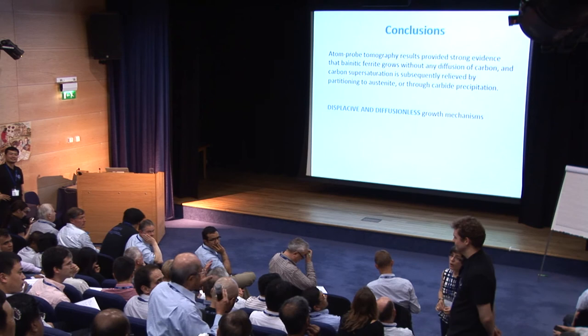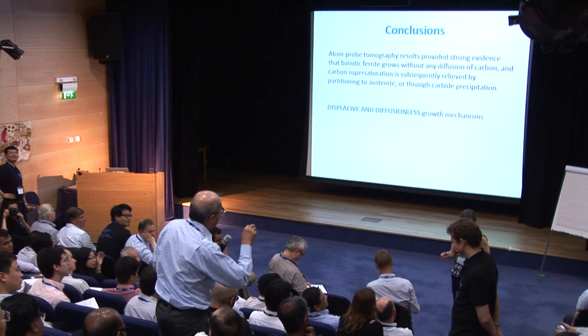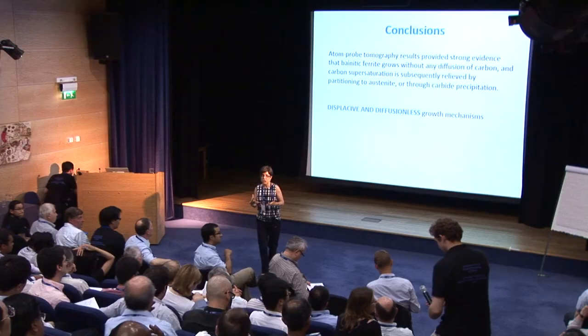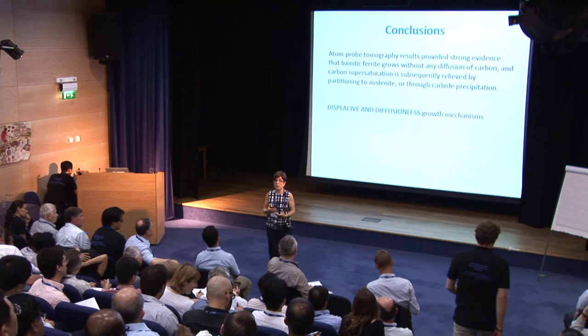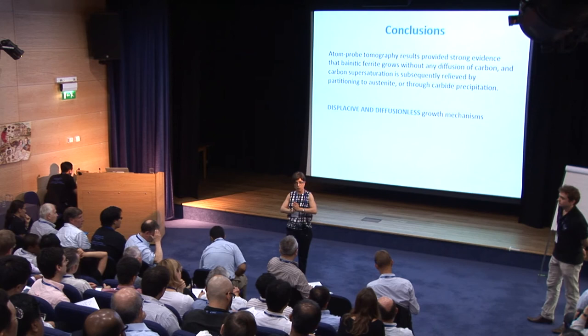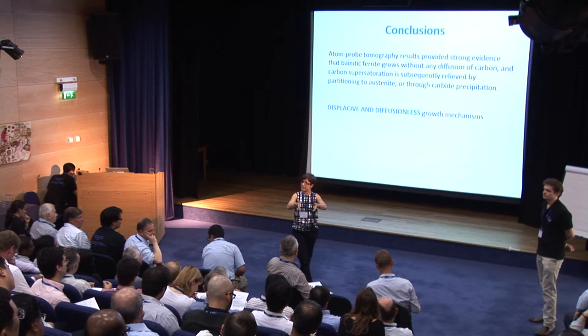Question: The formation of a nucleus of carbide also needs a jump of carbon atoms — isn't that diffusion? Answer: In the bainitic structures, we have seen the carbon supersaturated in bainitic ferrite, and carbon enriching the retained austenite at dislocations. If we have cementite precipitation — interlath cementite precipitation — that is evident by TEM or atom probe tomography. In terms of nanoclusters or carbon clusters, what we have seen is that with longer ageing, much later than the transformation has completed or during a subsequent tempering, those carbon-enriched dislocations evolve into carbon clusters, and those carbon clusters are the perfect nucleation sites for epsilon carbides.